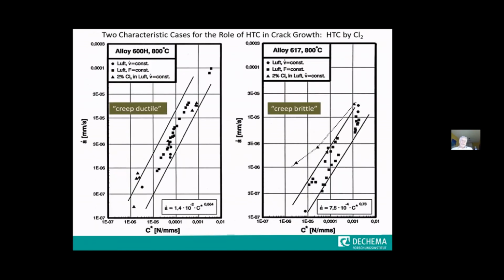You can do the same thing for a much more aggressive environment, which in this case was 2% chlorine gas in air. You see that the creep ductile materials are again much more tolerant to corrosive attack with regards to creep crack growth, but still, those are the chlorine values, you have a small acceleration here. Those are the air values here. But as soon as you move to the stronger materials, the creep brittle materials, and this is the chlorine value here, you can see there's at least 1 order of magnitude in acceleration due to the presence of corrosion. As a conclusion, one can say that the creep ductile materials are less prone to an acceleration in creep crack growth by the presence of high temperature corrosion than the creep brittle materials.